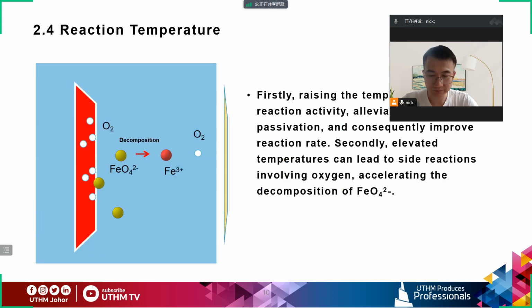The fourth factor is the reaction temperature. The influence of the reaction temperature on the electrochemical synthesis of ferrate can be summarized in two main aspects. Firstly, raising the temperature can enhance the reaction activity, alleviate passivation, and consequently improve the reaction rate. Secondly, elevated temperature can also lead to side reactions involving oxygen, accelerating the decomposition of the ferrate.